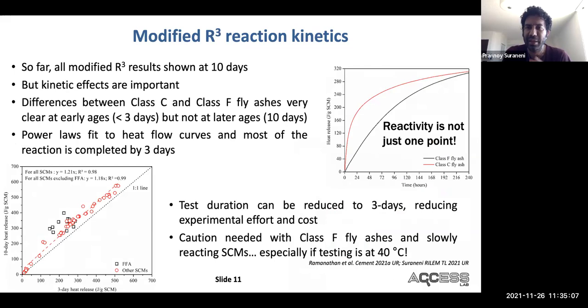What I mean by that is if you take this particular graph, this is the class C fly ash and this is the class F fly ash. Now I'm showing the heat release as a function of time. If you take only the 10-day value, then you're going to say that, oh, the class C fly ash and the class F fly ash give very similar reactivity values. And that's correct at 10 days, but that's ignoring the entire path of how they got there.